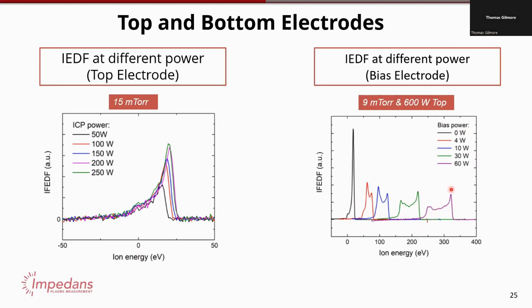I mentioned earlier the etch rate is a function of ion energy. So now you have a big wide spread of ion energies, all of which have different etch rates. Also note the sensitivity of power going from 0 to 4 watts. From a floating potential to a small bit of power can have a large change. So small variations in power can cause fairly large changes in the ion energies, which could take you from etching into not etching, or take you to a different mode dealing with the materials. This is where the issues start arising when you're running a tool for months in a row and you have to do maintenance. It's in part to solve these sorts of issues.